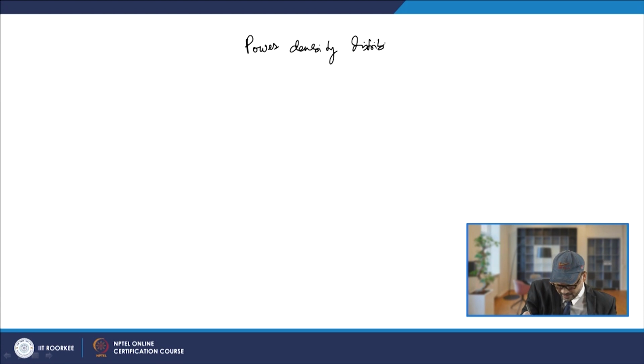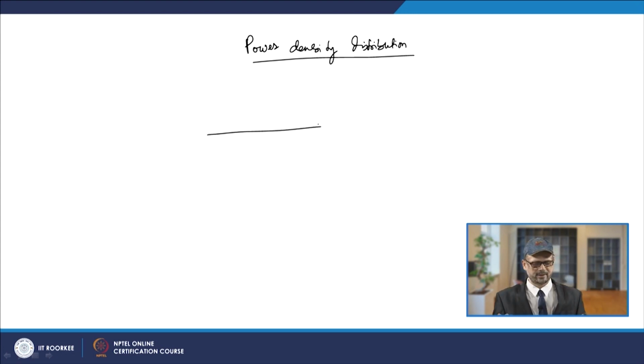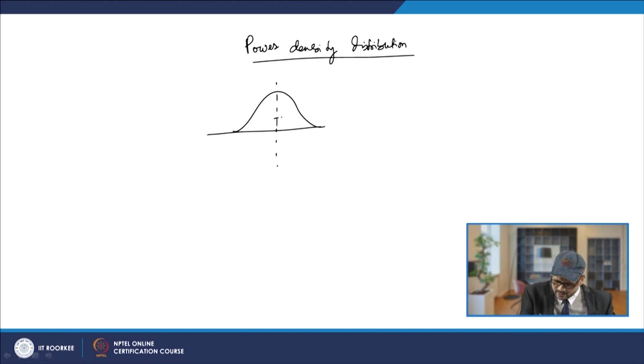Now, you can understand that if you have the different power density distribution, you will have the different weld shape. So, if your power density distribution is the Gaussian type, we take that Gaussian shape. So, if you take that power density distribution as the Gaussian one, so what we see is that if this is like 20, then you have 40 and 60. So, watt per meter square, that is the power density. Now, for such cases, if you take the weld shape, so weld shape will go like this.